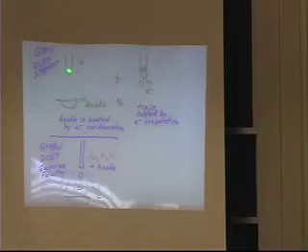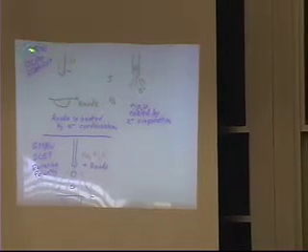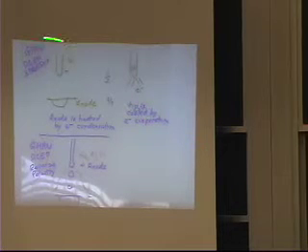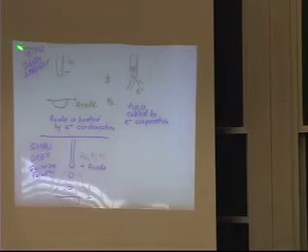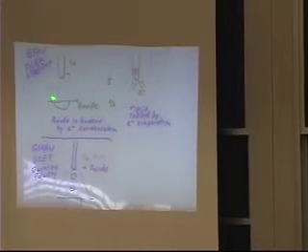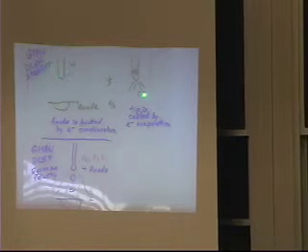That might be 25% of the heat goes into this tungsten electrode and heats it up, and you have to keep it cool, usually because you shroud it with a little copper. You put in a little copper collet, copper carries the heat away. But that tungsten gets hot. It's glowing red hot at about 2,000 degrees centigrade while you're welding. But tungsten melts at 3,300 degrees centigrade. But the anode gets 2/3 of the heat, and the tungsten only gets 1/3 of the heat.